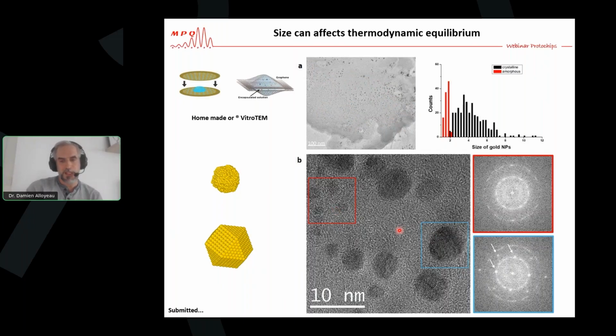And when you look at them at high resolution, you realize that you have two populations. One is amorphous nanostructures in a size range from 0 to 2 nanometer, and you have crystalline nanoparticles in a size range from 1.8 up to 10 nanometer. You can clearly see that on this high resolution image and on the Fourier transform, where you see only the structure of the graphene, and the crystalline nanoparticles where you see the characteristic reflection of gold structures.